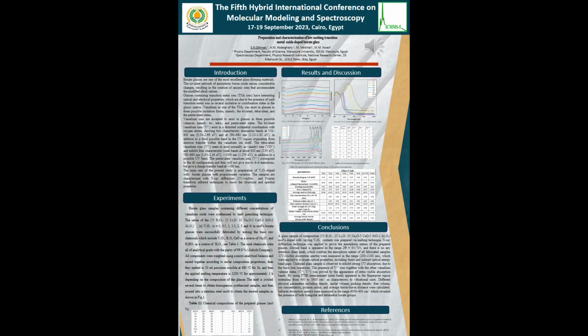X-ray diffraction was applied to prove the amorphous nature of the prepared glasses; a broad band appears, and there is no sharp peak detected, which confirms the amorphous nature of all fabricated samples. UV-visible absorption spectra were measured in the range 200 to 1100 nanometers to evaluate optical properties, including direct and indirect optical energy band gaps. The undoped glass sample exhibits strong UV absorption due to trace iron impurities. The presence of V3+ ions together with the other vanadium valence states, V4+ and V5+, was proved by the appearance of extra visible absorption bands. By FTIR measurement, some bands appeared in the fingerprint region extending from 400 to 1600 cm-1, characteristic of vibrational units.